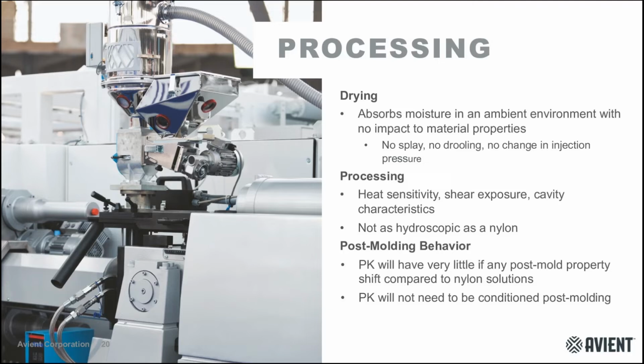And what that means is that while processing, you tend to want to stay away from long residence times. Anything over an hour is not recommended, but that's the case with most materials. Other than that, the material is very robust and will be a great offset for nylon in terms of what you're used to in processing. You're not going to see any kind of changes really in pressures, and the material should process fairly well.